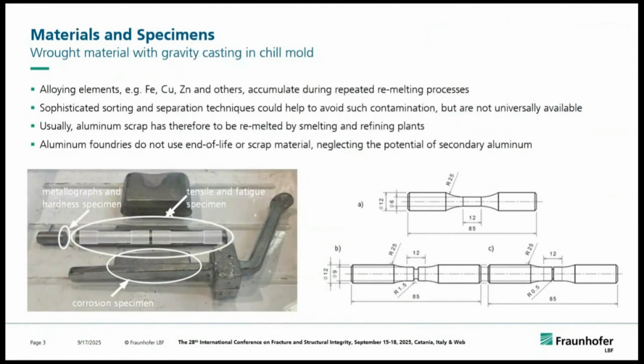So when we look a bit deeper into the specific sub-chapter and topic we worked on, as I said, it is an aluminium silicon manganese alloy produced with gravity casting. And at the end, when we talk about recycling and reuse of aluminium, we might have the problem that during the recycling process, additional fractions of iron will gather in the recycling aluminium. We will have problems with copper and zinc that, due to the recycling process, will gather in the recycling alloys. And the question is, how much effort can we spend in terms of CO2 emissions and so on to clean up those alloys on the one side, or leave them as they are, because we can prove that the fatigue strength and integrity of a component at the end can still be met.